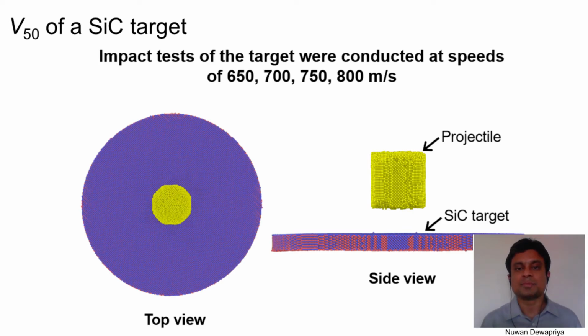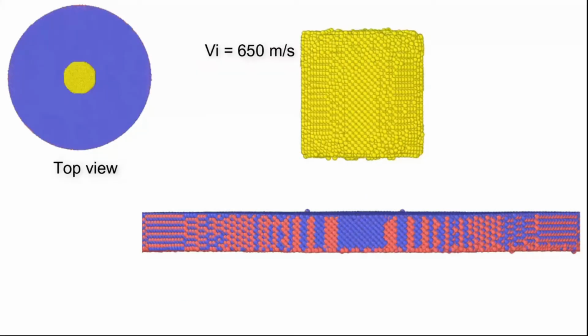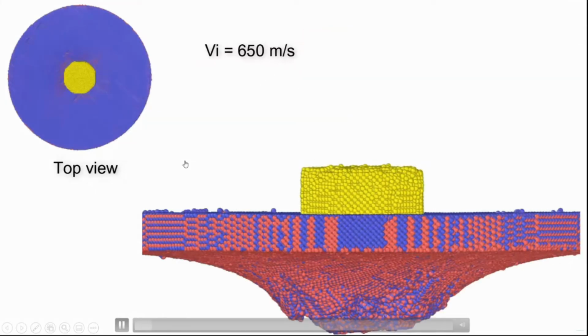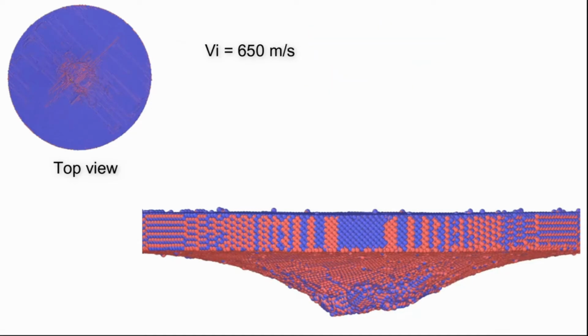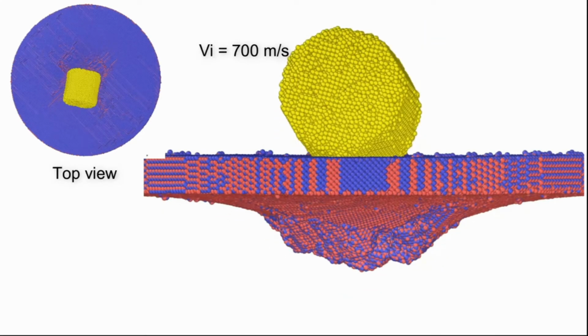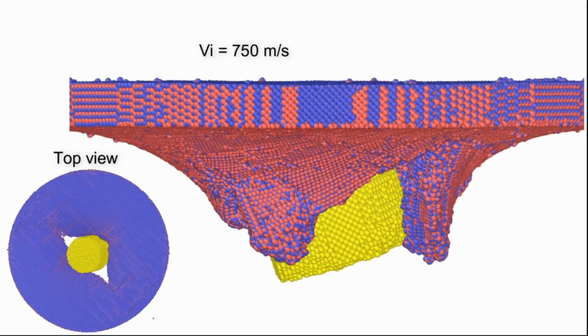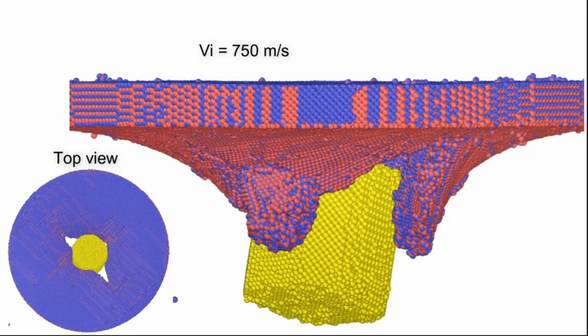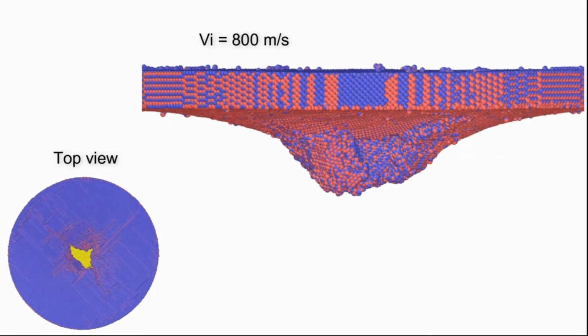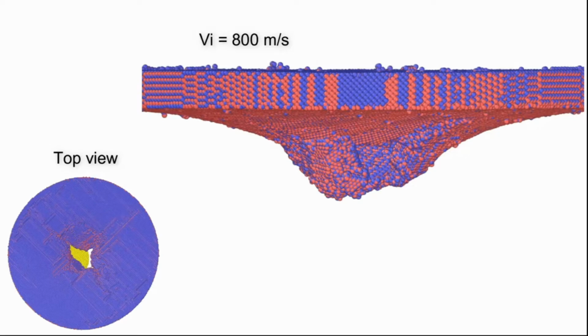We conducted 4 impact tests on identical targets with impact velocities ranging from 650 meters per second to 800 meters per second. This movie shows the 4 impact tests, where in this case the impact velocity is 650 meters per second. We can see the projectile bounces back at this velocity. Now the impact velocity is 700 meters per second, now 750. When the impact velocity is 800 meters per second, the projectile completely penetrates the target.